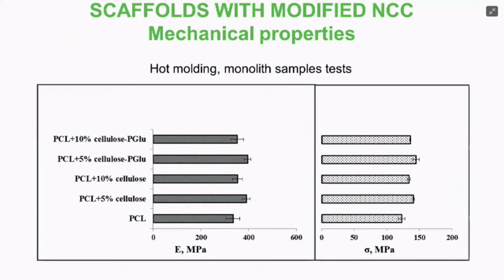We can say that all tested materials demonstrated plastic nature of deformation with high deformation resources. When compressed to 80%, none of the samples began to collapse. As we can see here, the introduction of neat or modified nanocrystalline cellulose into the polycaprolactone matrix contributed to an increase in mechanical properties. In turn, modification of nanocrystalline cellulose did not lead to a noticeable change in mechanical characteristics of the material under tested conditions. The properties of mixed materials, of composite materials, at the same filler contents are almost identical,